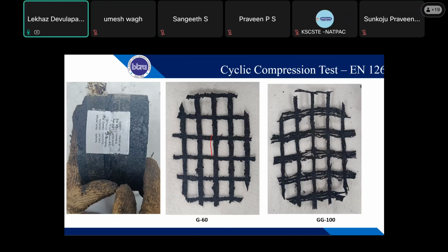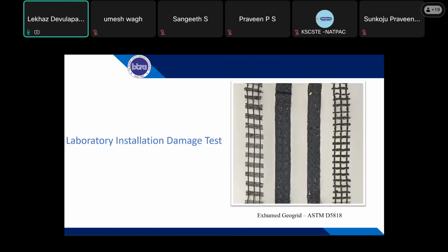And when it comes to the geogrids, we can see some sort of damage. We can clearly see at this junction the geogrid has been damaged. So then we thought we needed to do an installation damage test on our geogrids.